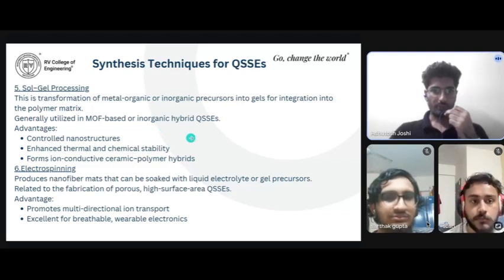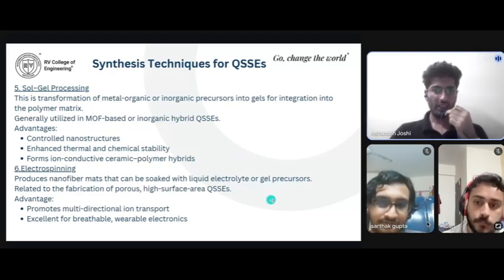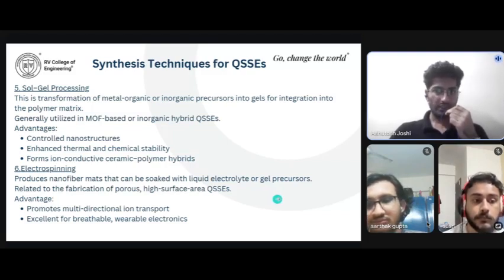Now we have electrospinning and solution casting. Last but not the least, electrospinning is often combined with solution casting for creating porous nanofibrous mats. Its mechanism includes a high voltage applied to a polymer solution, ejecting fine fibers that are collected on a substrate as a nonwoven mat. Its application includes QSSEs ideal for breathable, wearable devices, and they are also used in high-rate zinc-ion batteries. Its advantages are extremely high surface area, increased electrolyte interface, promoting multi-directional ion transport, and being excellent for breathable and wearable electronics. Next slide.